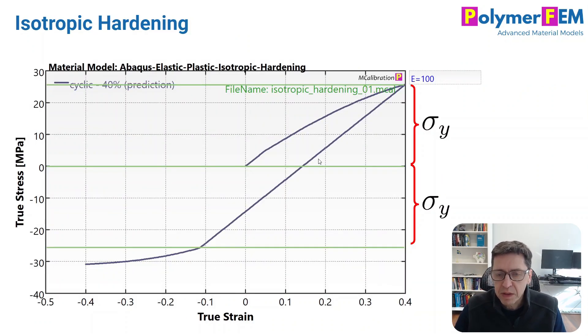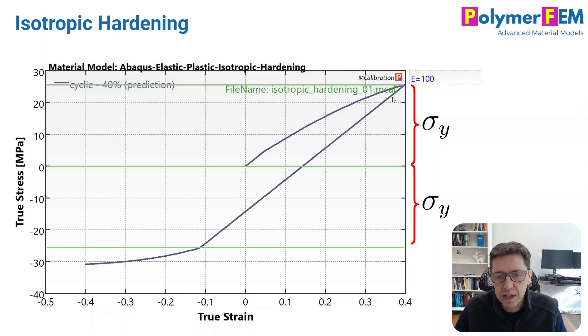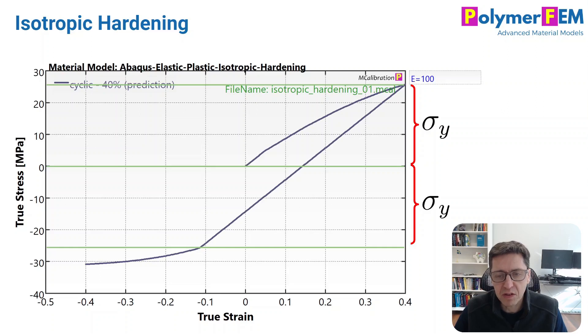It's helpful to look at loading and unloading curves as a mental picture of what's going on with these plasticity models. For isotropic hardening plasticity, with the origin in the middle, I pull the specimen to about 40% strain and 25 MPa, then unload. You get totally linear elastic unloading until reverse plasticity occurs, showing a symmetry between tension and compression. This is not good for predicting the response of polymers and plastics — maybe for metals, but not polymers.